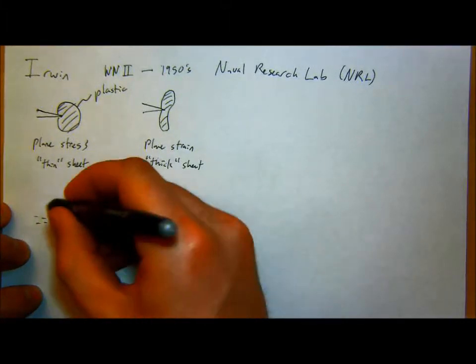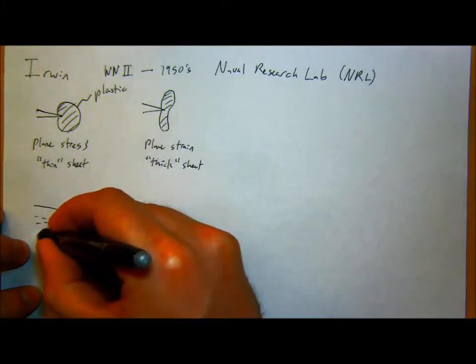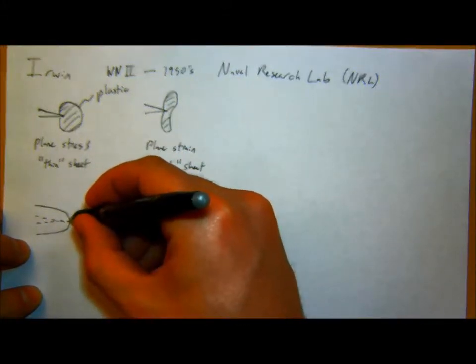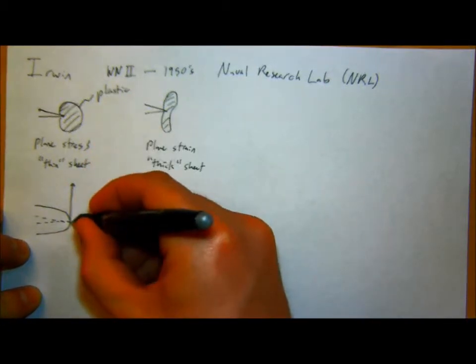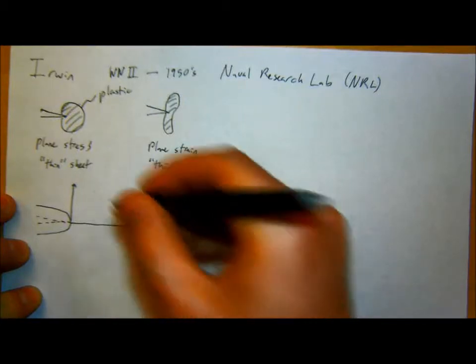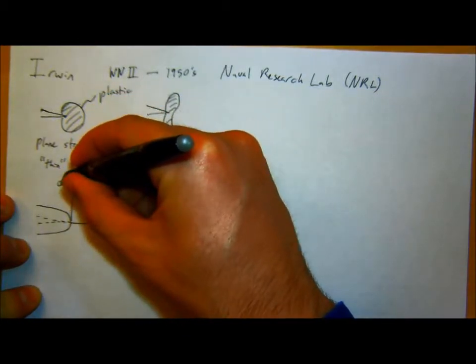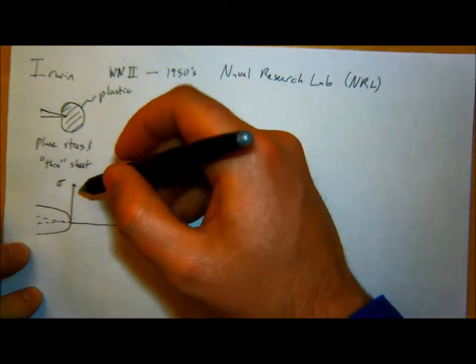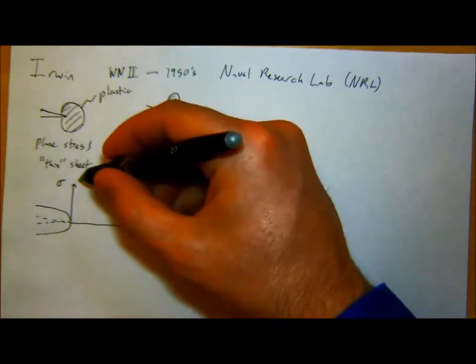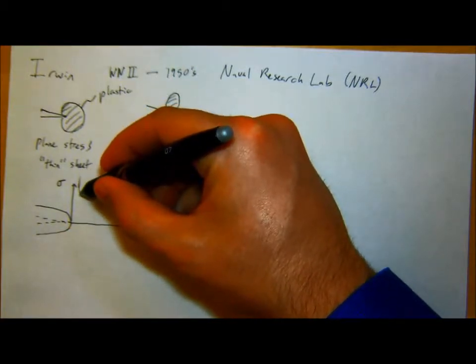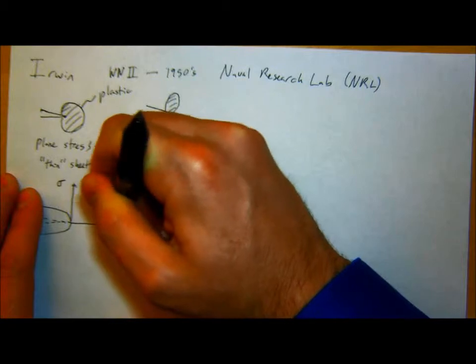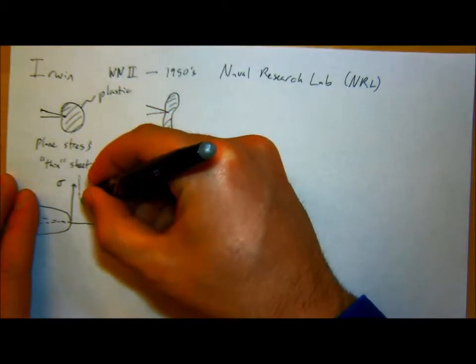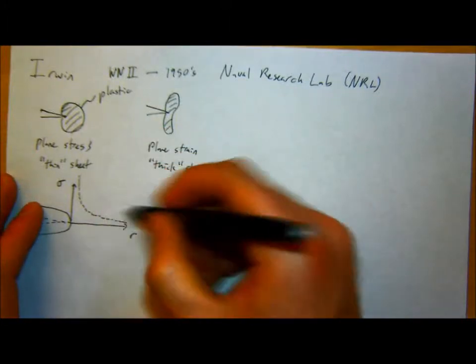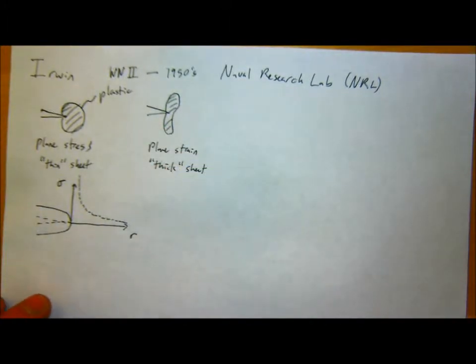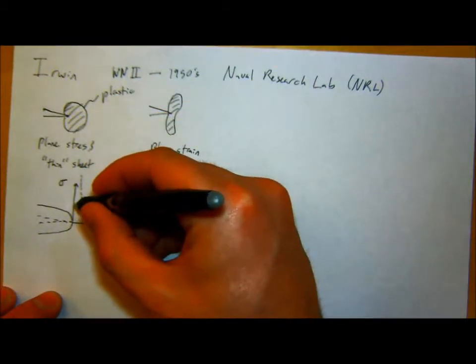Theoretically now, if I look at the stress some distance r away from the root of the tip, if I look at the magnitude of the stress, theoretically, remember, if I have an infinitely sharp crack, that stress goes to infinity. So it kind of goes up to infinity, and then it would come down here and plateau. I'm going to draw this with a dashed line instead. Theoretically, it goes up here to infinity, and then comes down and plateaus to some far field stress that we're applying. But realistically, because of this plastic zone, I'm going to hit some yield strength of the material, and it's going to be plastically deforming around here, and then eventually it'll come back down to that far field.